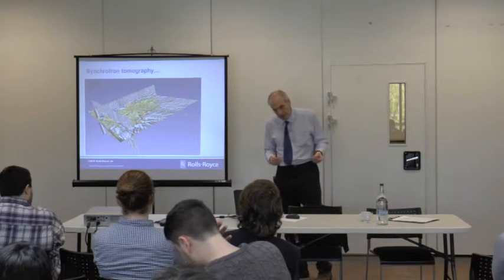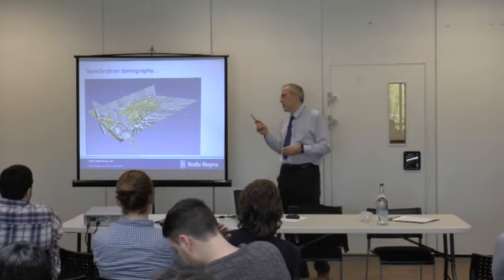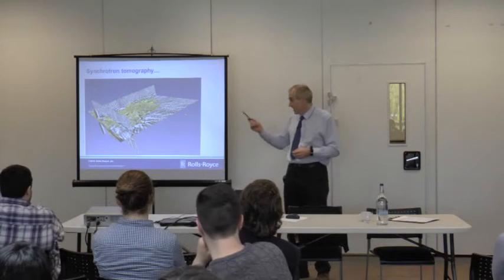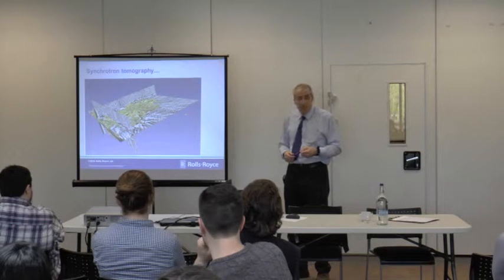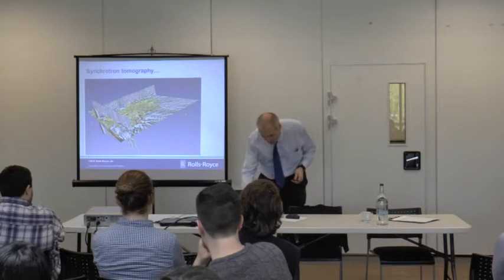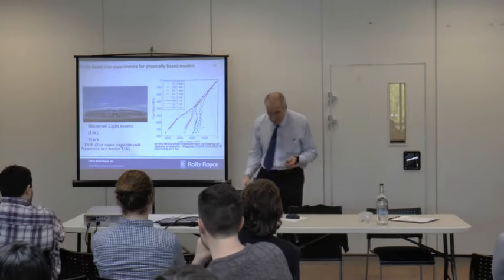You can get to high spatial resolution with it. You can also punch through quite a lot of material. So we can stick photons through about 4 or 5 millimeters of titanium, something like that, which is getting quite useful size. So that's okay, but it's not the be all and end all.